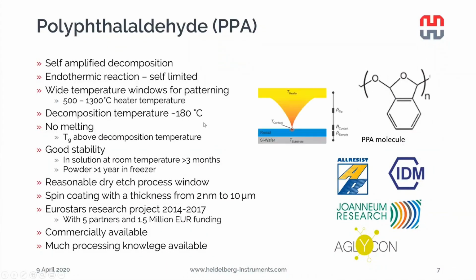So here we review the heat transfer in the tip shortly again, as this heater temperature that I mentioned sits actually on top of the tip, and the decomposition temperature is measured at this interface temperature between the tip and the resist. So we lose a lot of temperature by the heat transfer from the heater to the tip. Therefore, we need to set a much higher temperature than the actual decomposition temperature.